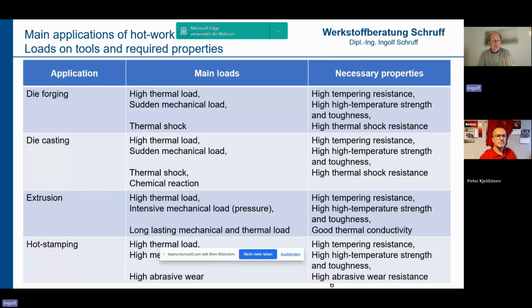In die casting, for example, aluminum, we shoot liquid aluminum nowadays with temperatures above 700 degrees into the steel die, into the mold of hot work tool steel. And this mold is filled within fragments of a second. And even when you look at these large underbody structures, which you have in some cars today, then you shoot more than 120 kilograms of liquid aluminum within a fragment of a second into such a die. You can certainly imagine how sudden these thermal and mechanical loads come up.